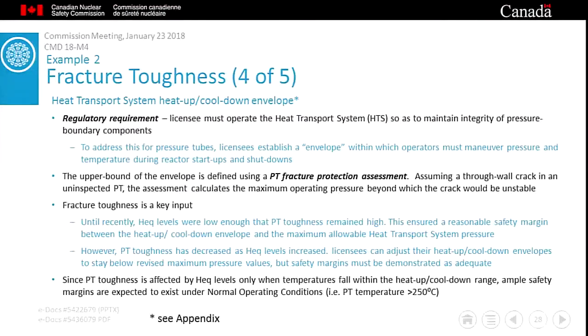Early in life, it was pretty straightforward to devise a heat up and cool down envelope. Pressure tubes contained only a small amount of hydrogen, so they were pretty tough. In contrast, steady increases in pressure tube hydrogen equivalent levels makes the current situation a bit more complicated. With falling fracture toughness levels, licensees have found it more difficult to define a heat up cool down envelope that will allow them to pass a fracture protection assessment.